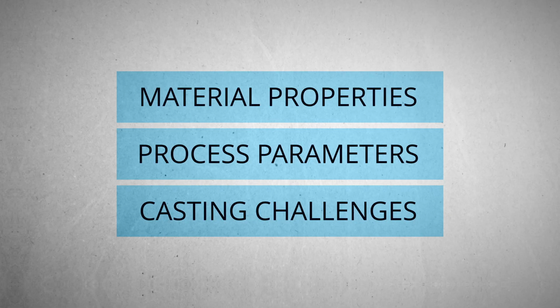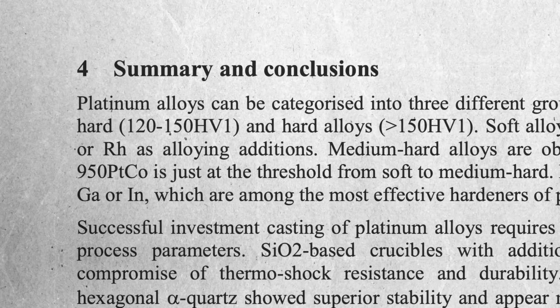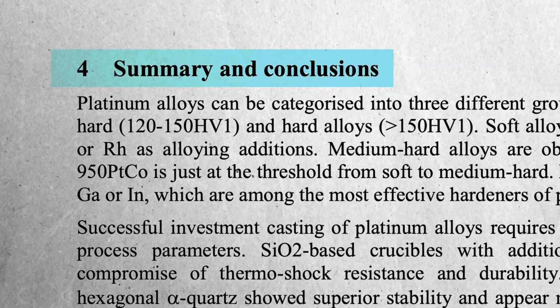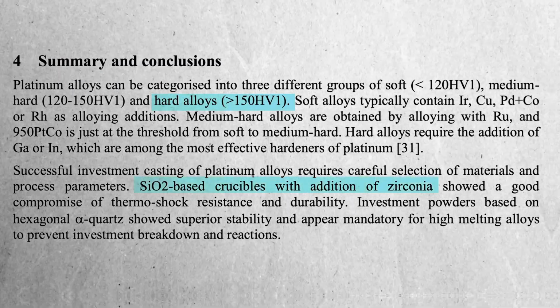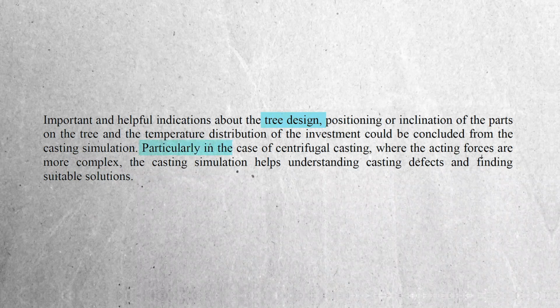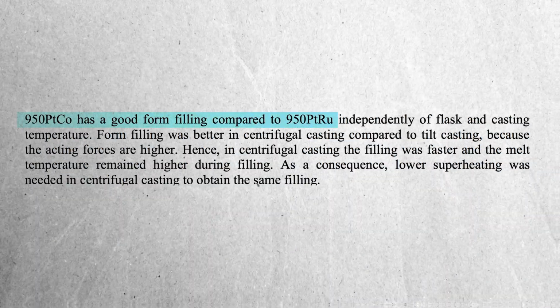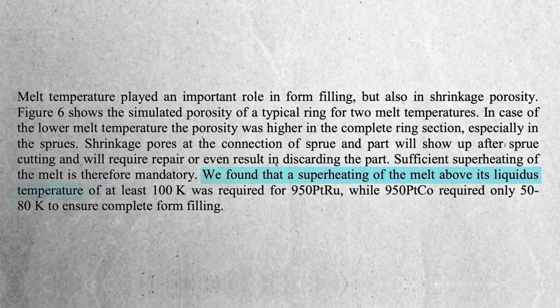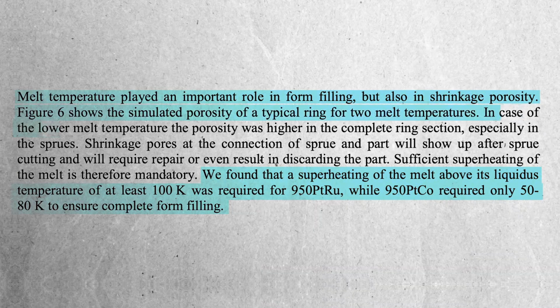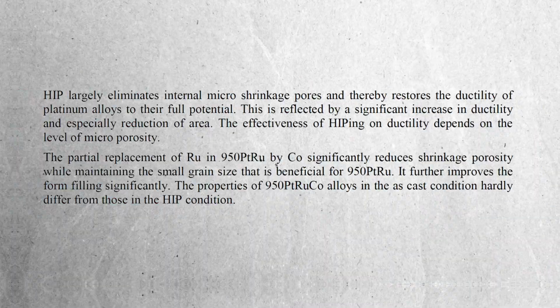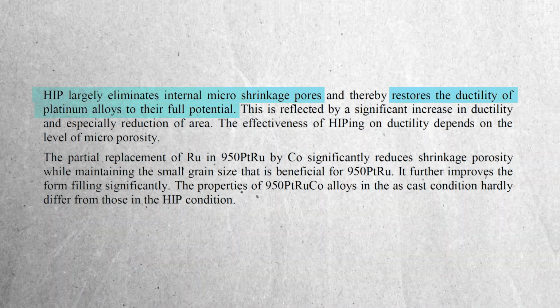The title suggests casting challenges, process parameters, and material properties. A bit broad, yeah? And each of these topics, honestly, deserves its own episode, if not a mini-series, to get into all the details. If you flip to the back and read the summary and conclusions, the paper covers material used in casting, mainly referring to crucible and investment powder; tree design, especially for centrifugal casting; form filling between different alloys, and also between centrifugal and tilt casting; temperature, to superheat your alloy or not to superheat, ultimately related to the causes behind casting porosity. And finally, the paper also touches a little bit on HIP, hot isostatic press, which previously we've covered on PlatinumABC.